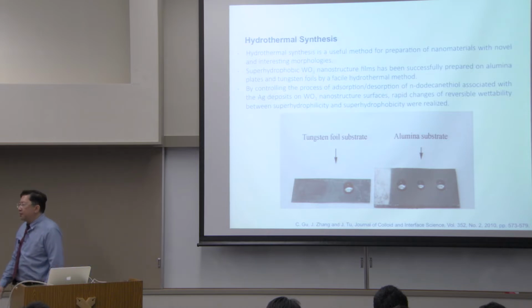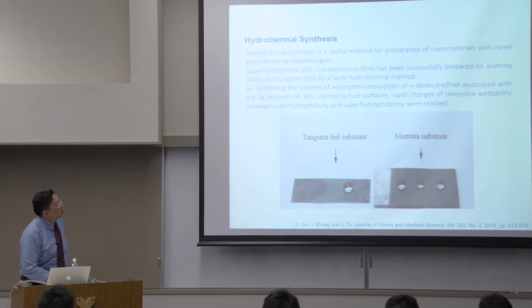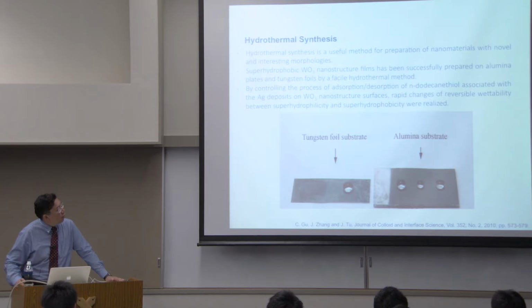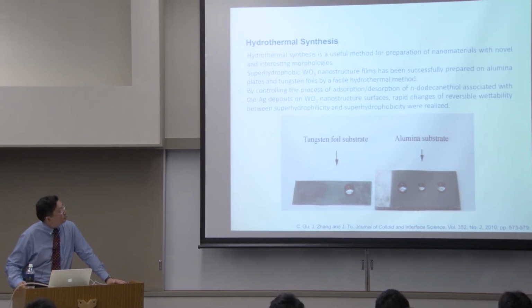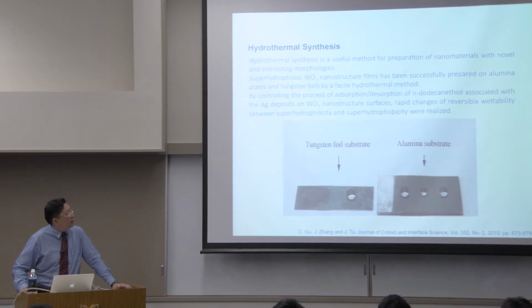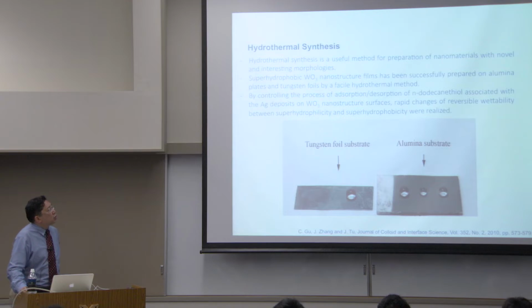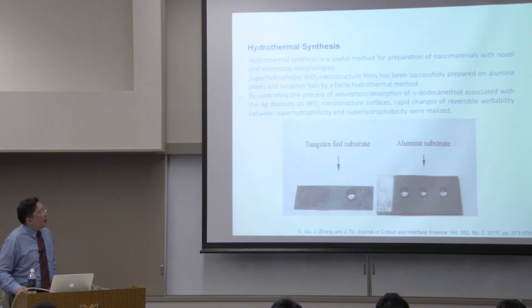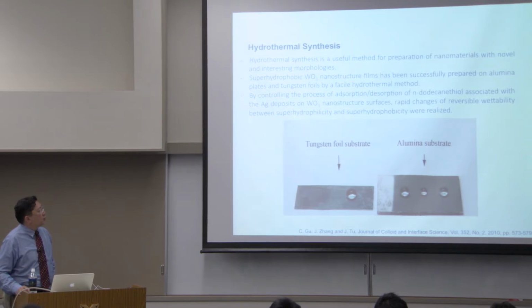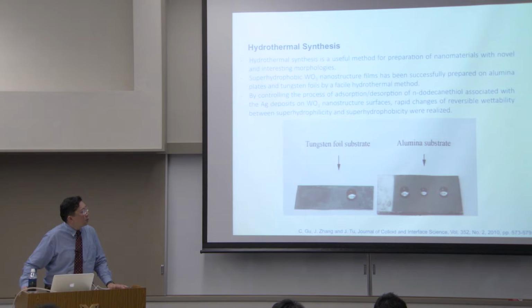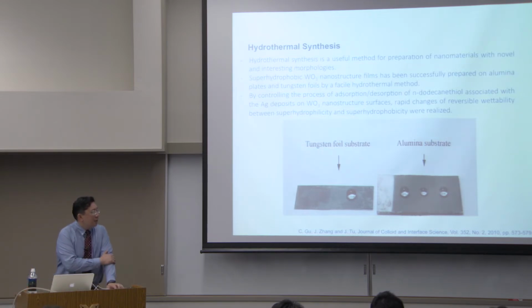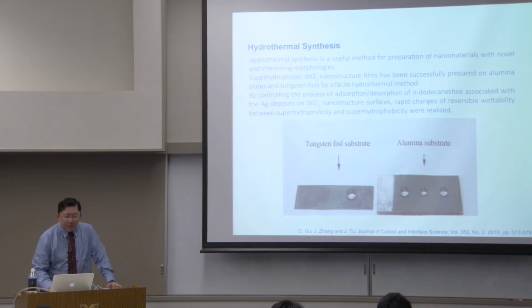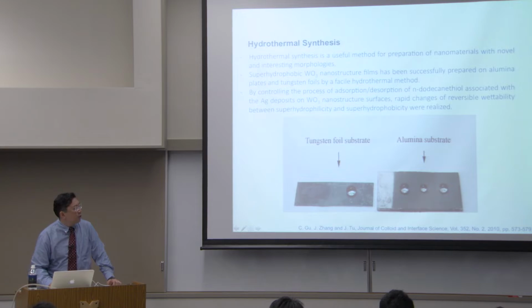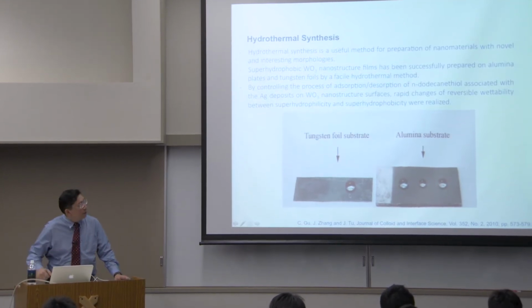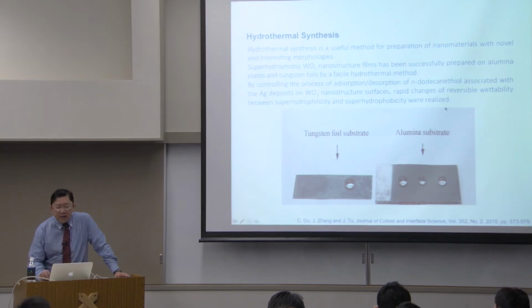Another example is based on hydrothermal synthesis. In this case, tungsten oxide nanostructure films were prepared on alumina plates and tungsten foils using a hydrothermal approach. What happens is that you control the adsorption and deposition of dodecanethiol associated with silver, deposited on the tungsten oxide surface. We don't have the SEM structure or optical microscopy here, but you can guess that underneath the surface there's a roughness factor that has also been modified with the presence of the dodecanethiol.